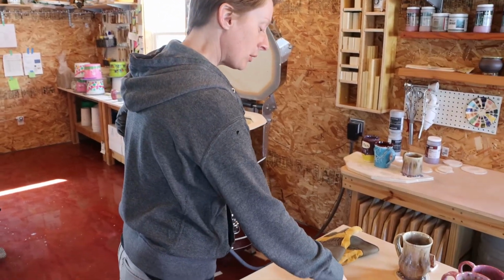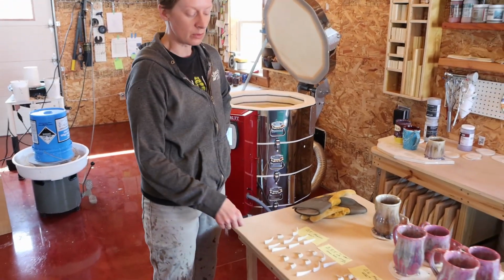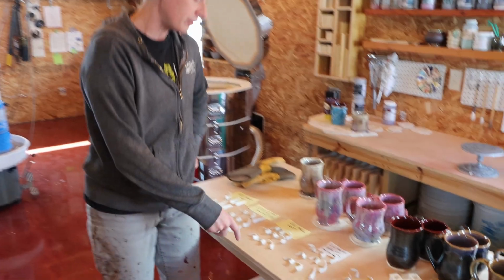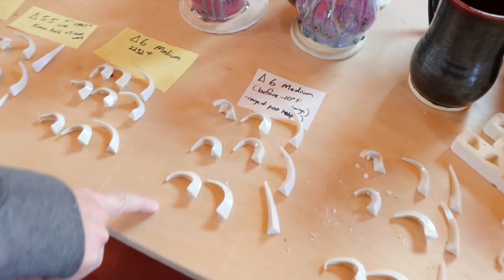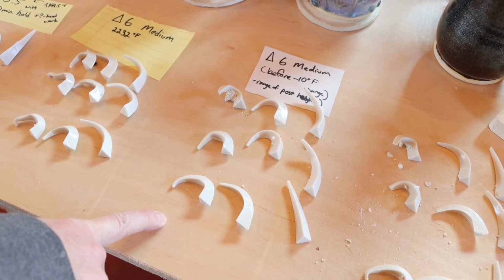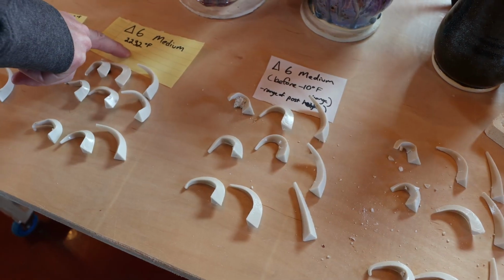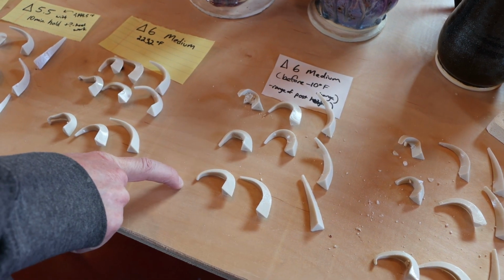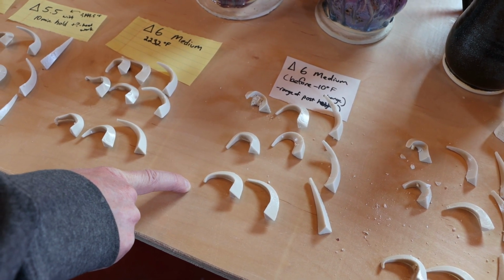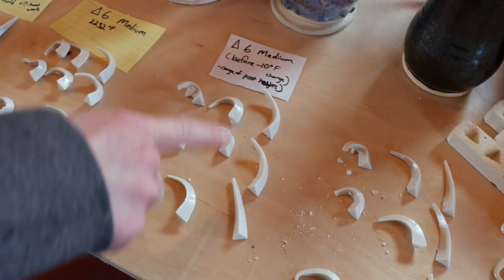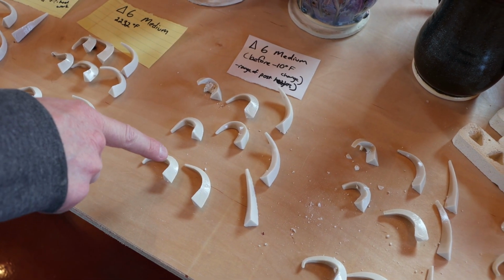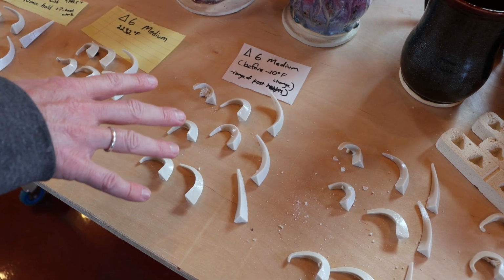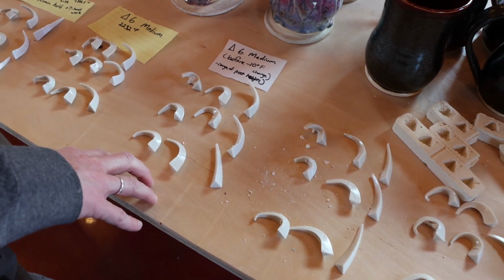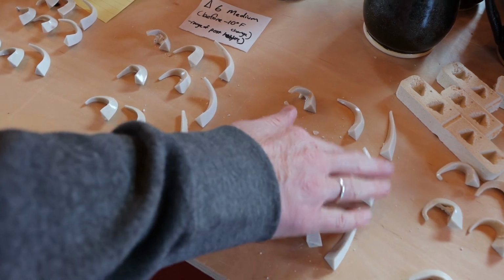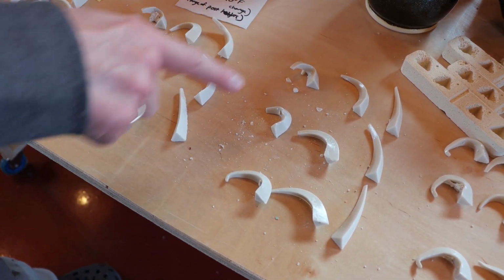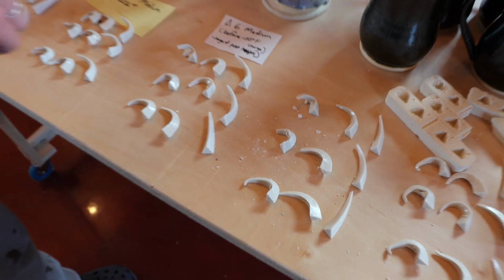The only thing about the cone 5.5 with a 10-minute hold is that certain glazes don't like the hold. So the next one we did was just a regular cone 6, the way the kiln is rated, again just in case maybe I screwed something up. This was empty with just shelves to bounce the heat off of. Then the next firing was before the cone offset, supposedly a regular cone 6 but with nothing in it other than shelves. Then this next firing had a little bit of glaze ware in it, and this was after our cone offset of minus 10 degrees Fahrenheit.